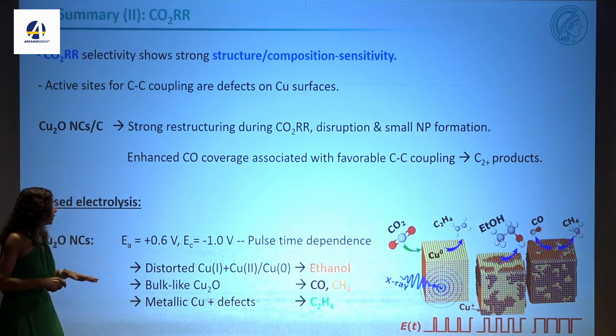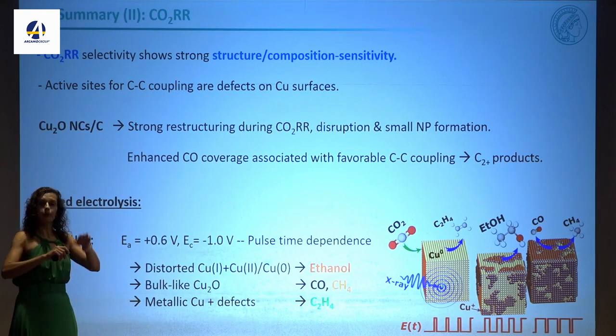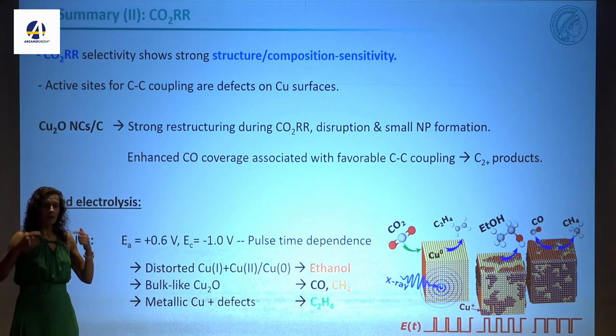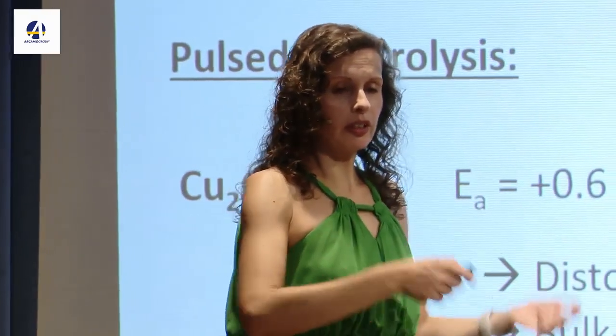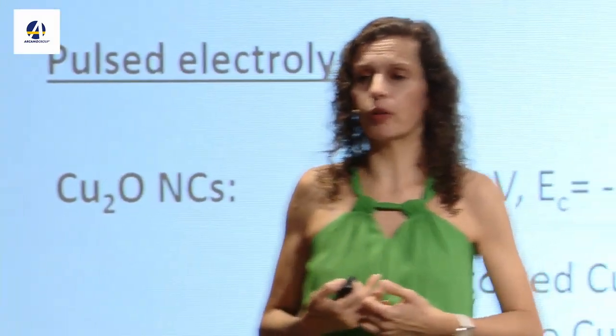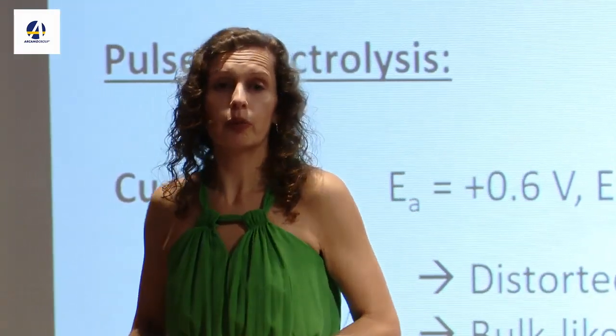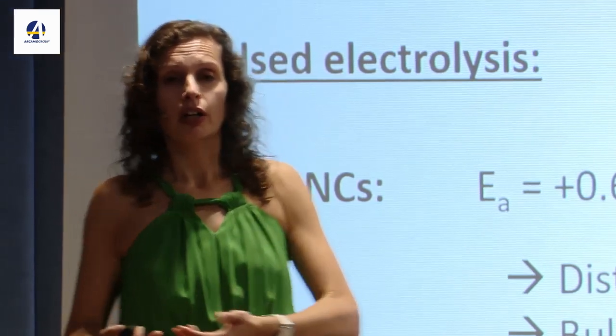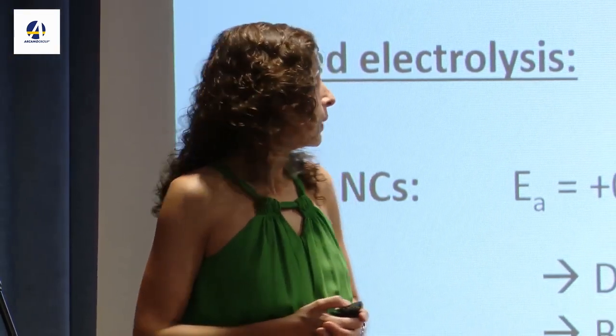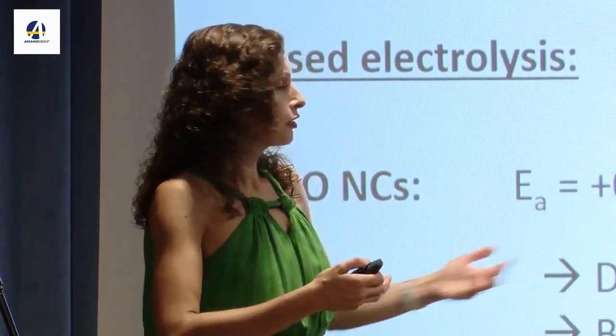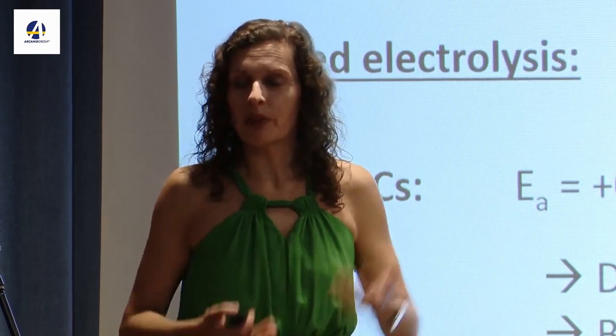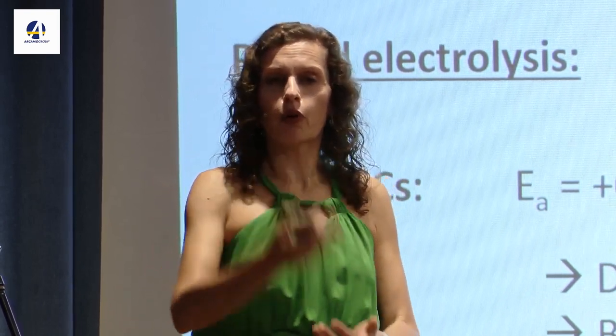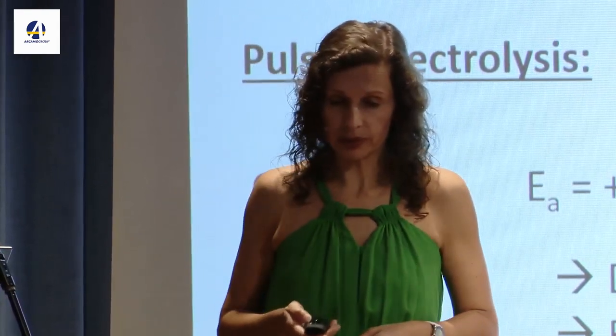again in composition. You can tune this by applying potential pulses, and give you an idea that thermal catalysts and electrochemistry have a lot of things in common. We have a different activation way, so we don't heat, we are using an electrical potential, but the catalysts for CO2 conversion are the same. The problematic of having metallic copper or copper plus or having brass is the same, but you go through different intermediates tuned by this environment.